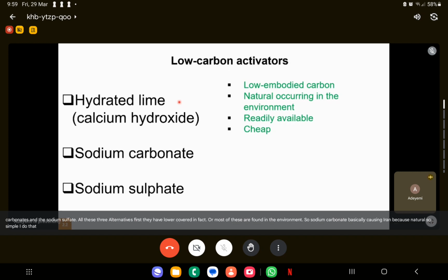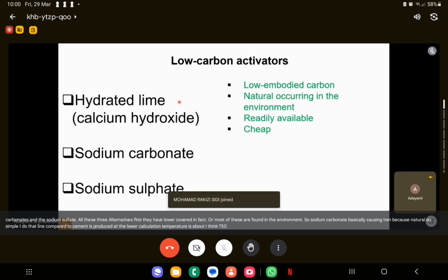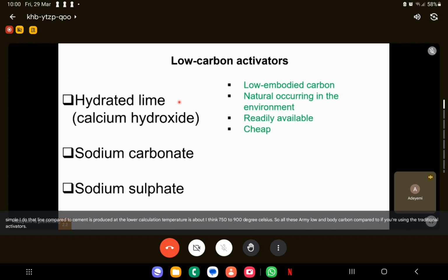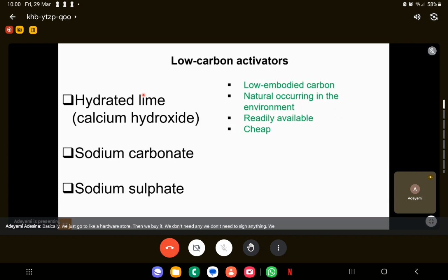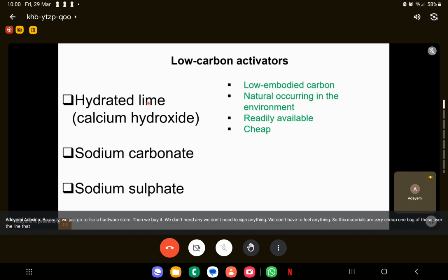Hydrated lime, compared to cement, is produced at a lower calcination temperature, about, I think, 750 to 900 degrees Celsius. So all these have a lower embodied carbon compared to if we're using the traditional activators or if we're using Portland cement as the binder. And these materials basically they are so cheap. So the hydrated lime we use in our lab, basically we just go to a hardware store, then we buy it. We don't need to sign anything, we don't have to fill anything. So these materials are very cheap. One bag of the hydrated lime that we use is like $8.